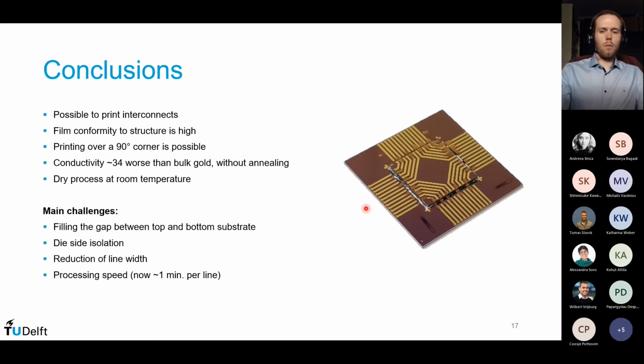So to conclude, it is possible to make these interconnects with a nearly unlimited step size. All you need to do is change the programming of the printer, and you can change how high you want to make your step. Film conformity is high. It follows every feature that you print on. And even a 90-degree corner is no issue. Conductivity is worse than bulk gold. Now, of course, this is not an annealed sample, which could improve it partially. And it's highly porous. So that can be a benefit, but also a problem, because you have lower conductivity.